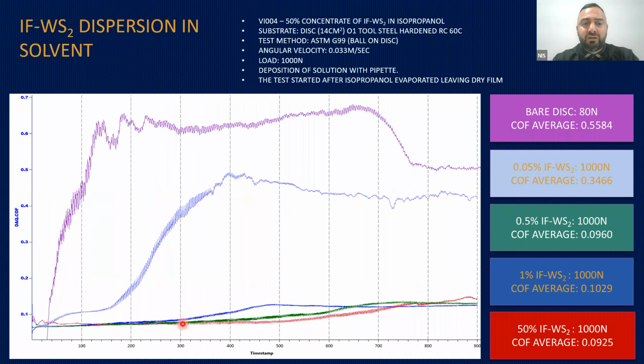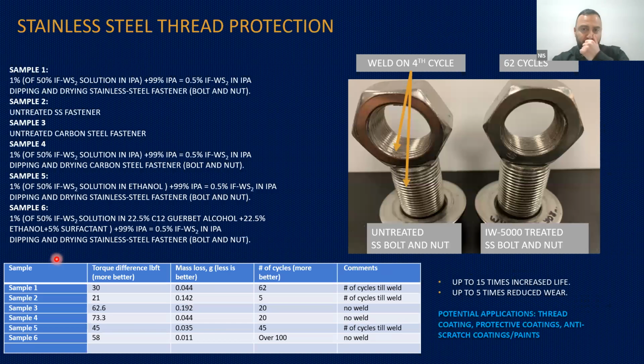Almost zero friction as a coating at the high loads compared to very high load uncoated surfaces. But what I wanted to show you, this one is also a very interesting slide showing the anti-galling effect on threads. So it can be used as a thread protective coating as well. The threads, if you're talking about big fasteners, there's a lot of contact pressure on the contacts, and that's really good for particles to provide protection for those applications, the threads.